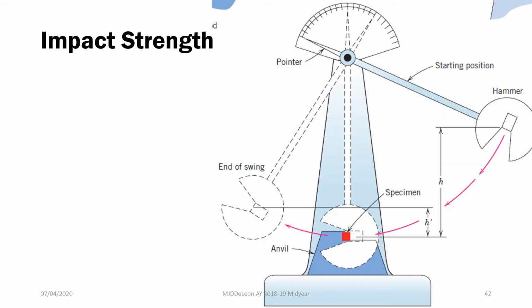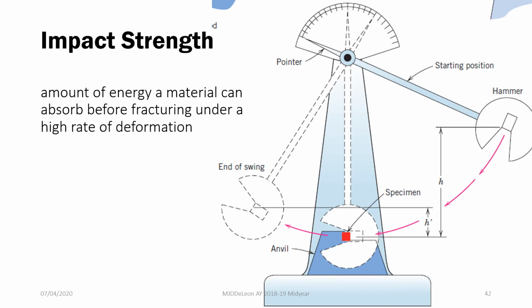To assess the toughness of your material, one of the most widely used tests in our materials engineering field is the impact testing. So in impact testing, we get what we call your impact strength. Impact strength is the amount of energy that a material can absorb before fracturing under a high rate of deformation. So we use impact testers, which just drop a load from a high position down to a low position.